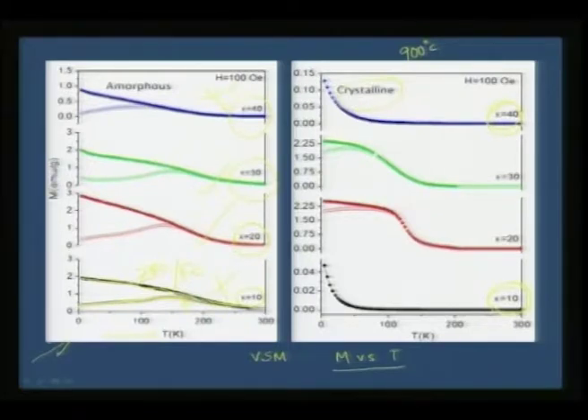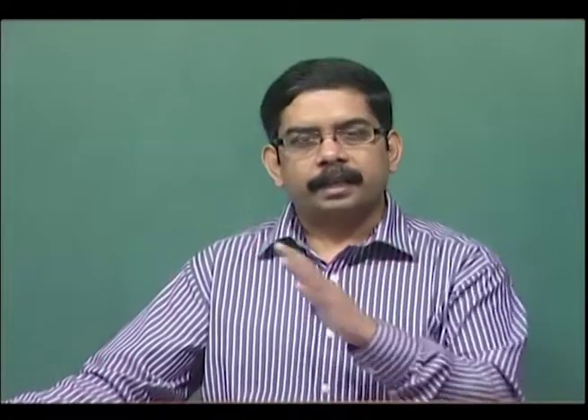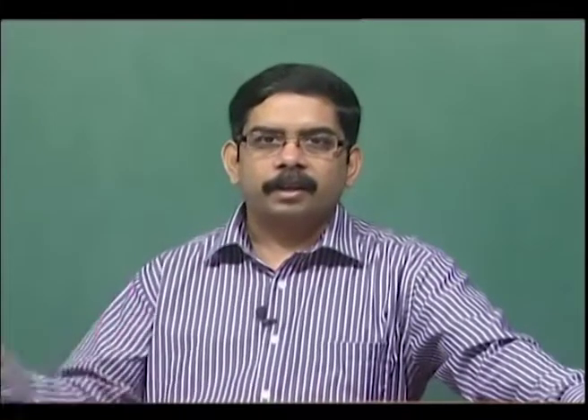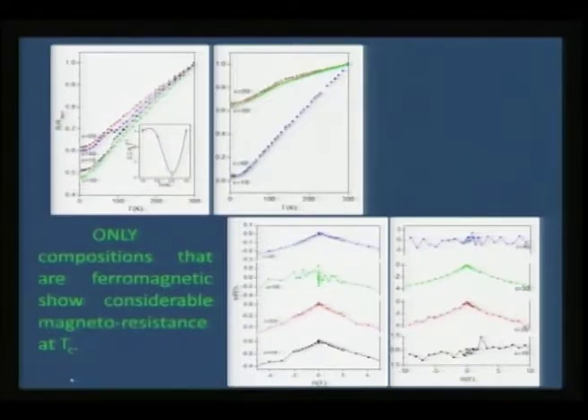So, what we can say is that although in bulk the compositions are known to show order disorder transformations leading to magnetic and non-magnetic phases, in amorphous form the interactions are totally different. As a result, you get magnetic phases throughout the entire doping concentration of platinum. This is one of the fascinations of studying nanoparticles, because when the band gap is altered, when we try to play with the finite size effects, then you can clearly manipulate or bring a drastic change in the magnetic property. And the same is true if you try to do rho versus T plot, that is the conductivity plot.